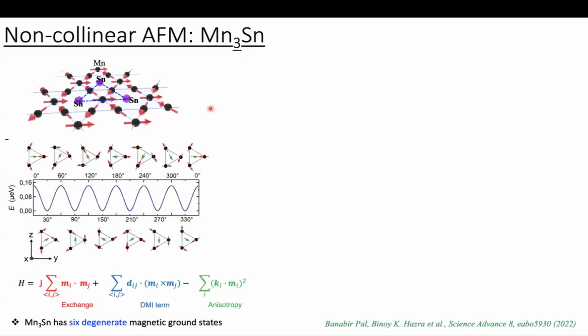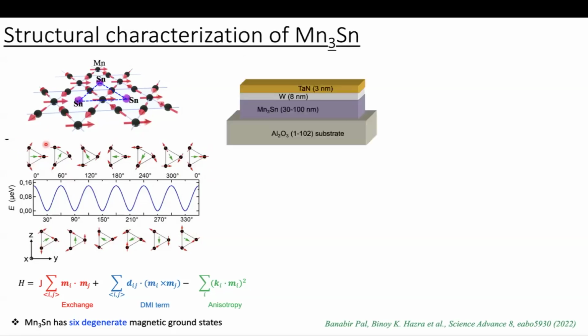So it has 6 degenerate domain structures, at 30 degrees. These are denoted by how the manganese spins are oriented, and the green arrow shows the net moment of this triangular system. So there are 6 degenerate ground states: 30, 90, 150, 210, 270, and 330. And these are the low energy domain configurations.